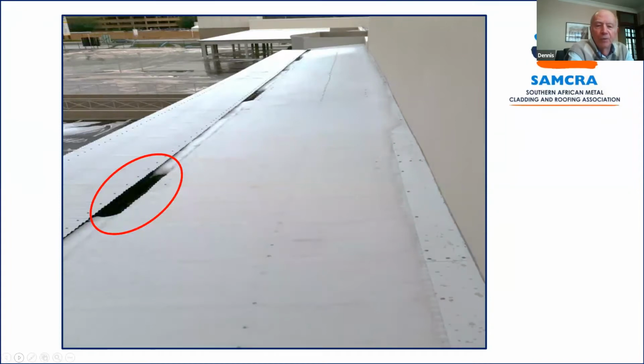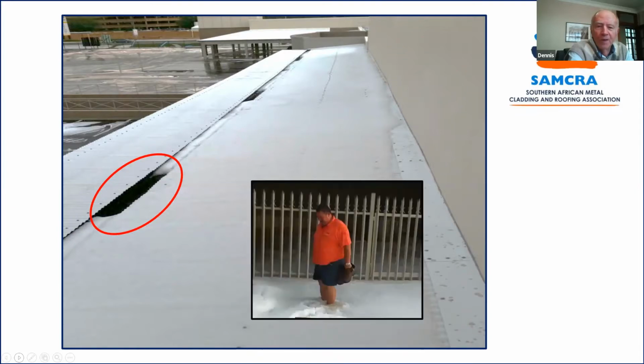And if you look at the next, that little insert, please, Denise. This was a roof in Klerksdorp in November 2014, and they had two very heavy falls of fine hail in a single afternoon. And you can see there that it ultimately ended up being around 200-300 millimeters deep. That was a guy standing on the ground, but on areas of the roof, and particularly the main roof of the shopping center, we had 200 to 300 millimeters of hail accumulate.